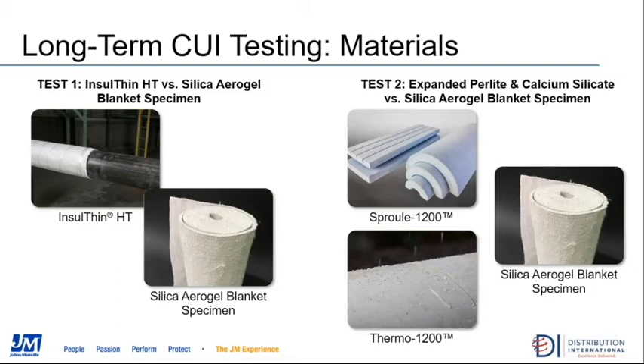So as Scott was saying, there's a secondary test or protocol that's been developed in the market, developed by some leading industry professionals. And we subjected a couple of our materials to this testing. We ran actually 2 separate tests. So you can see on the left there, test 1 was run with the Insulthin HT and Silica aerogel blanket. And test 2 was run with the Sproule perlite, the Thermo 1200, and the Silica aerogel blanket.